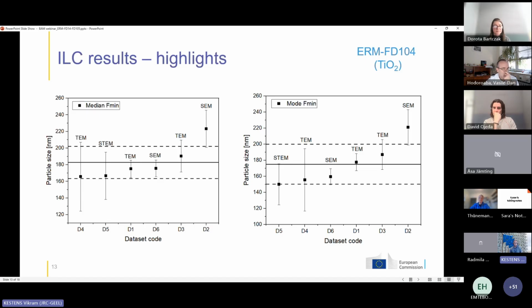So we had a lot of data sets. Here I only give a few results, but basically all the results are very similar in that respect. For example, here you see the results for ERM FD104, the titanium dioxide, and both the median and the mode value of the minimum Feret diameter. And you see that the results are overlapping the certified range. But you can see some differences in measurement uncertainty.